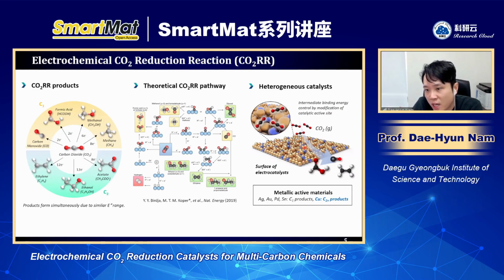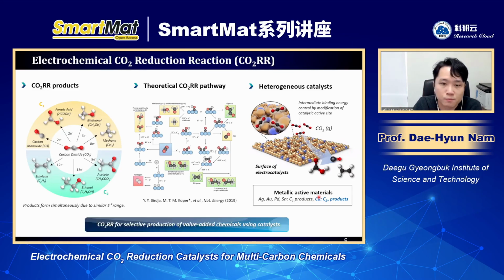These catalysts are composed of metal atoms such as silver, gold, palladium, or tin, which are very good for producing C1 chemicals. And if we have copper as an active material, it is good for producing C2 chemicals, because copper enables C-C coupling and CO dimerization. Today, because the title of this presentation is how to produce multi-carbon chemicals, we are going to talk about the copper-based catalyst.